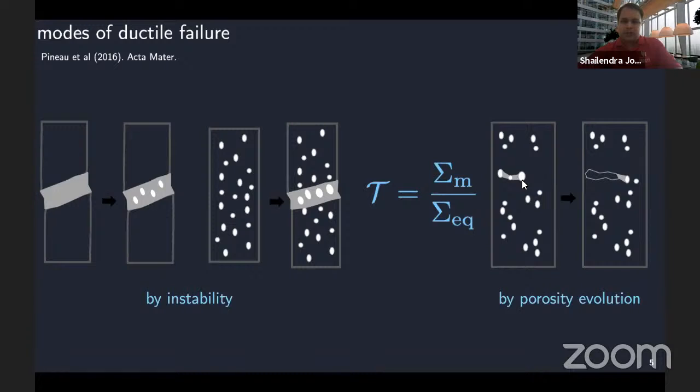And what happens is the voids nucleate, they grow, they coalesce into one another, and they form damaged zones, which also immediately introduces us to the multiple scales at which these processes occur. Plasticity, which is driven by slip and sometimes by other mechanisms like twinning that I'm going to talk about, interacts with defects in the form of the internal porosity or second phase particles that lead to nucleation of voids. These voids then form zones of damage, which we call mesoscopic zones of damage, which then interact with component scales to form macroscopic fracture phenomena. So that's something that is interesting.